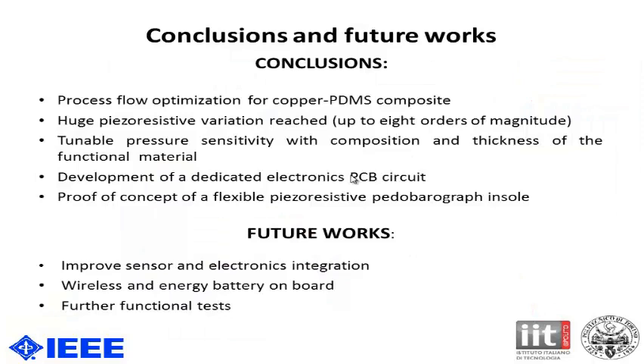So in summary, we obtained an optimized process for this copper PDMS composite. We obtained a huge piezoresistive variation of up to 8 orders of magnitude. We obtained a tunable pressure sensitivity, and we developed specific electronics for this sensor, and we did a proof of concept of a flexible piezoresistive pedobarographic insole.